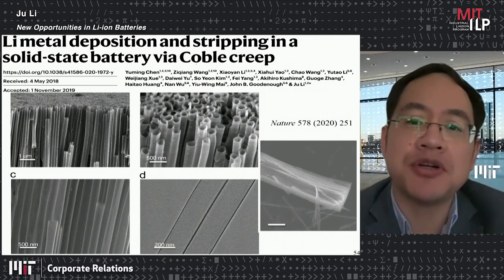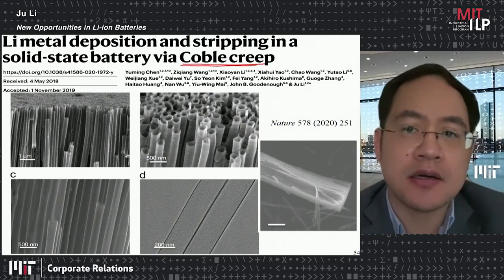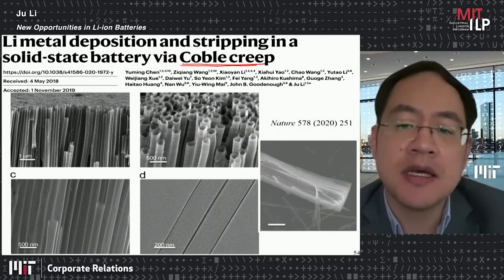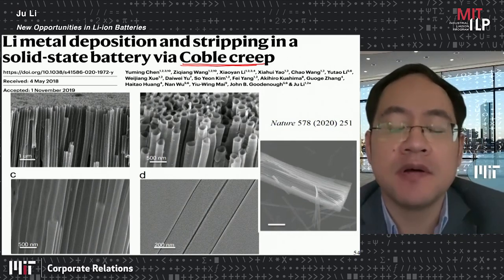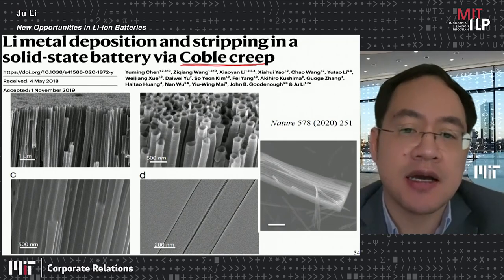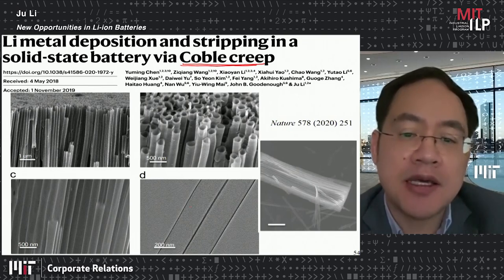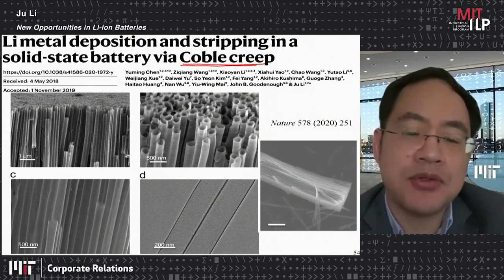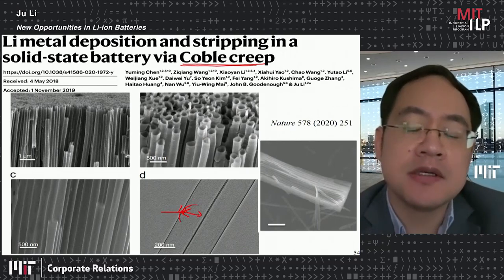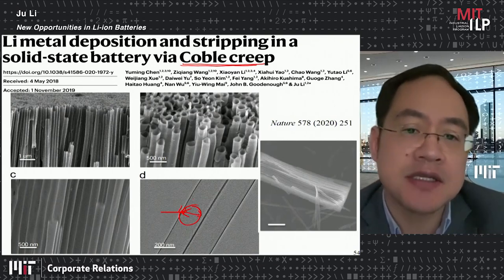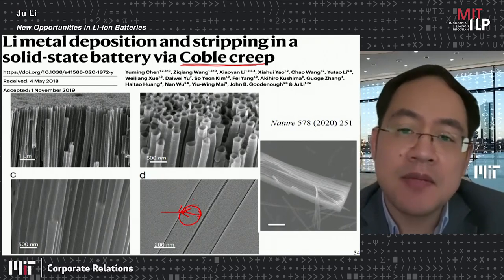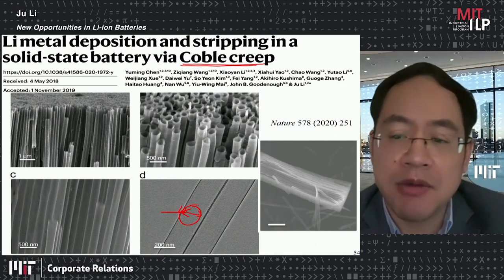Recently, we've shown that at room temperature, you can use the creep of lithium metal to drive the motion of the body-centered cubic lithium phase in these tubules. These tubules cannot be too thin, because the wall cannot sustain the mechanical stress. The diameter is at an optimal size of about 100 nanometers. This kind of system is able to wick lithium metal up and down, almost like a liquid at room temperature, just by electrochemical driving force in an all solid state battery.